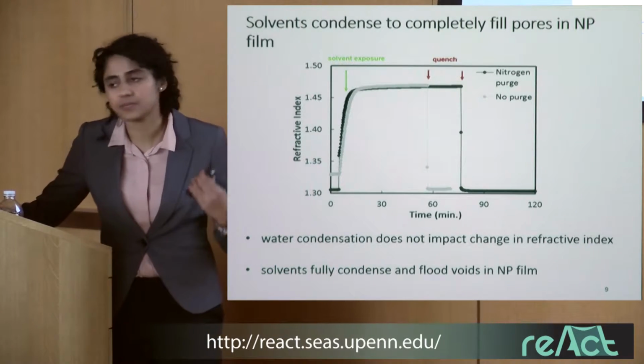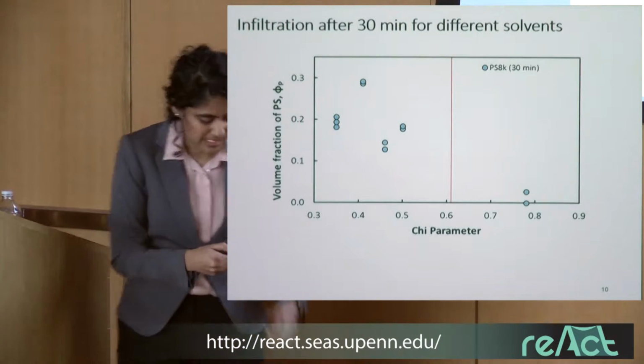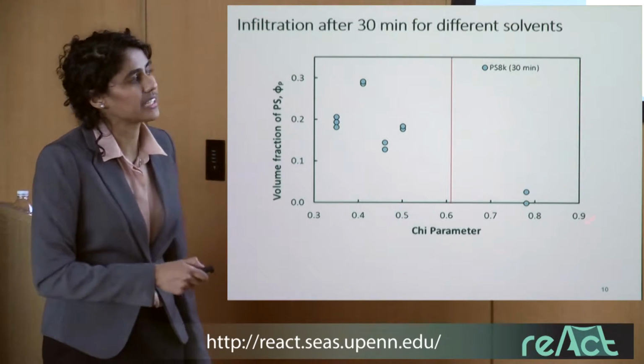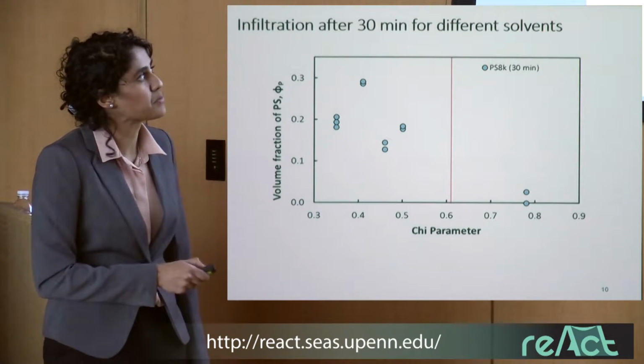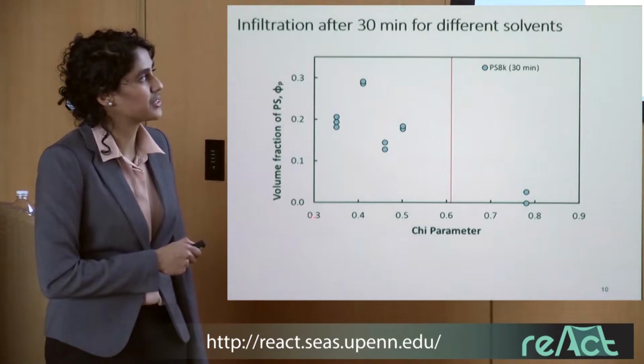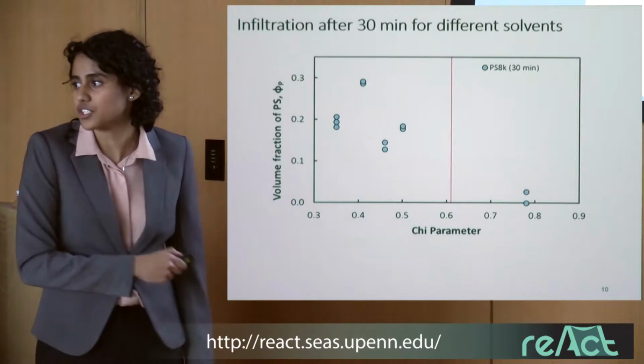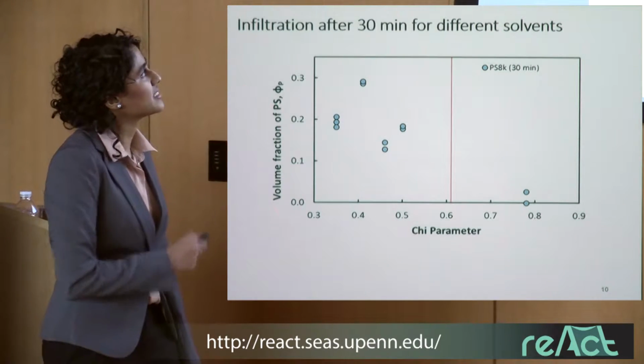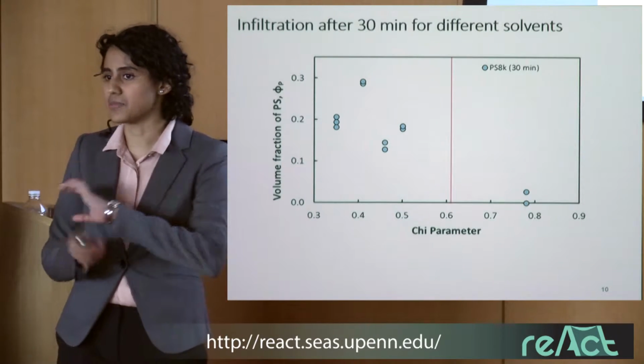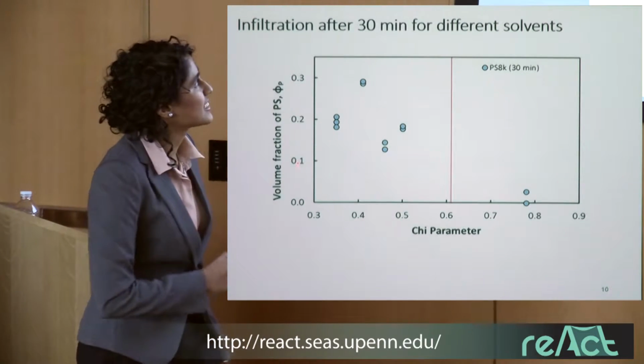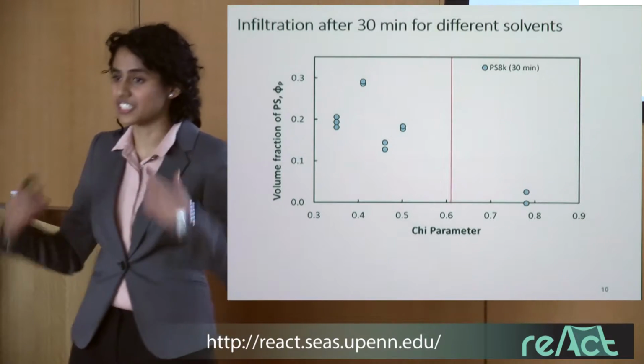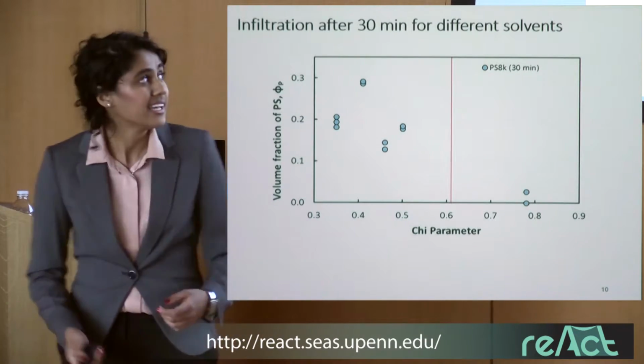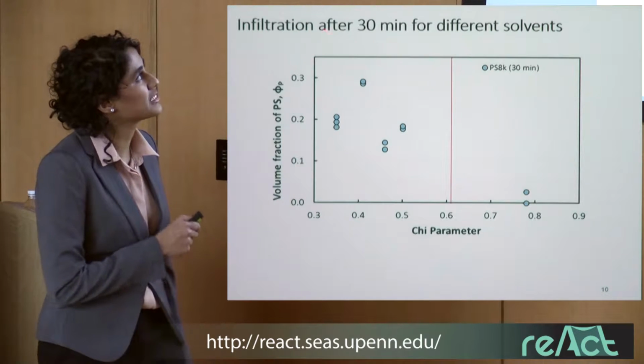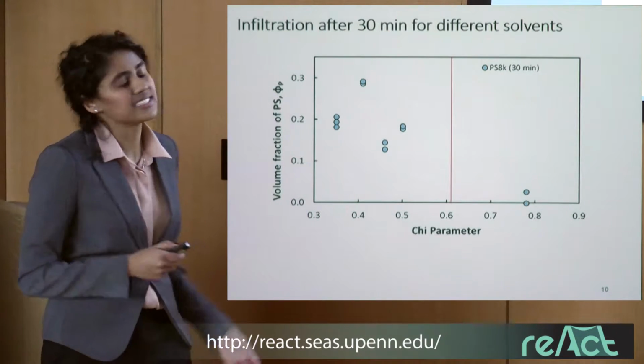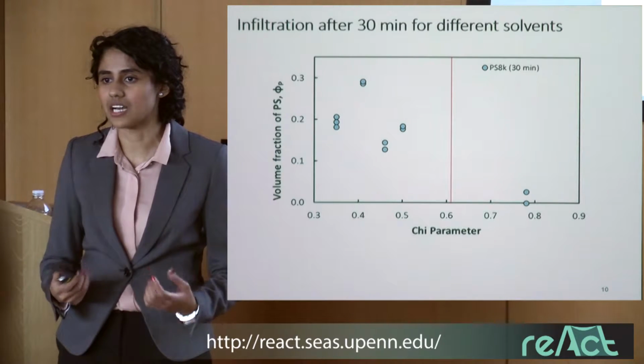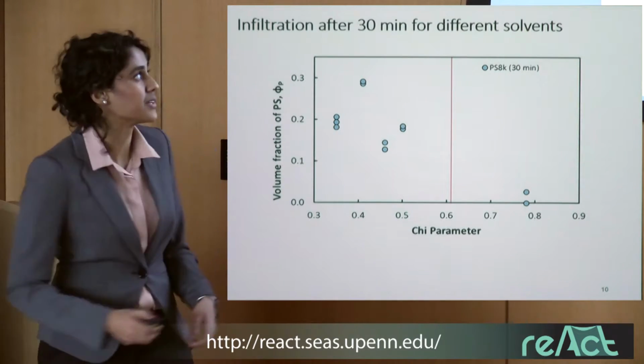So I tried this with many different solvents, and I've characterized the different solvents using a chi parameter, where this is basically my poor solvent regime, and this is good solvent. So here the solvent quality is decreasing as you go down the x-axis, and this is the volume fraction of polystyrene I have in my nanoparticle packing. And basically, I see that there's a decreasing trend as I decrease solvent quality, which is what we expect. My void fraction is roughly around 0.35, and within 30 minutes I can achieve pretty high filling of these nanoparticle packings with polymer.